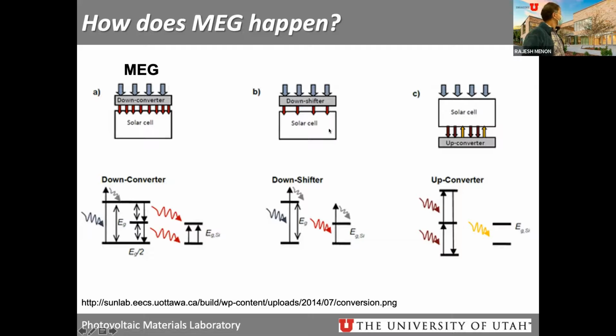So 1 blue photon now gave me 2 red photons and 2 electron hole pairs, essentially getting me external quantum efficiency larger than 1. The other way you can do it is something called downshifting, where, say, in this case, blue photons come in. I get the same number of red photons, but I have energy absorption such that I get an extra electron hole pair, which is shown here. So let's look at it energetically. Blue photon comes in. Again, the electron is excited way above the conduction band, relaxes rapidly, and then it emits a red photon. But a red photon now excites the electron hole pair much higher than the band gap of the silicon. And this extra energy can then be used to excite another electron hole pair rather than just relaxing to the band edge. That's actually not very common and not very efficient to actually do.